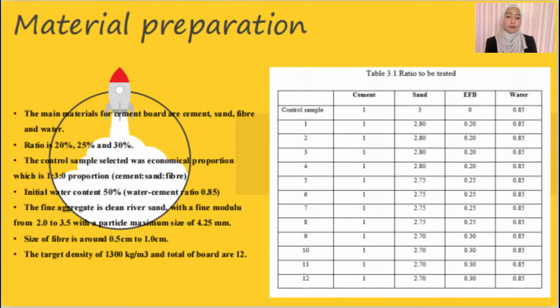This is my material preparation. The main material for cement board are cement, sand, fiber, and water. The ratios I choose are 20%, 25%, and 30%. The control sample selected is 1:3:0 proportion, which is cement, sand, and fiber. The initial water content is 50%. For water cement ratio, 0.85. The fine aggregate is clean river sand, with a fineness modulus from 2.0 to 3.5, with a maximum particle size of 4.25 mm. The size of fiber is around 0.5 cm to 1.0 cm.